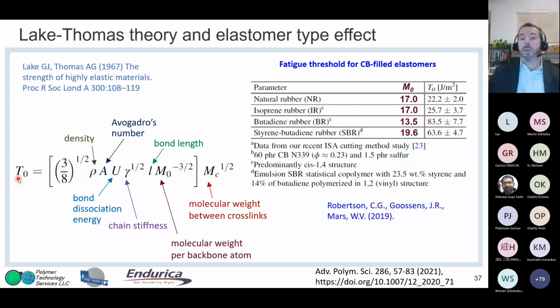And so we made some measurements on carbon black filled elastomers, different elastomer types: natural rubber, isoprene rubber. Obviously, chemically, these first two are very similar to each other, then butadiene rubber and an emulsion type SBR. And the M sub 0 is the molecular weight per backbone atom. It turns out to be 17 for polyisoprene, whether natural or synthetic. Butadiene rubber is much smaller at 13.5, and then SBR is 19.6 because of that heavy styrene group.